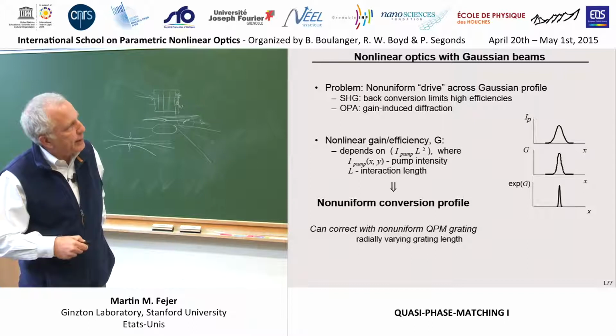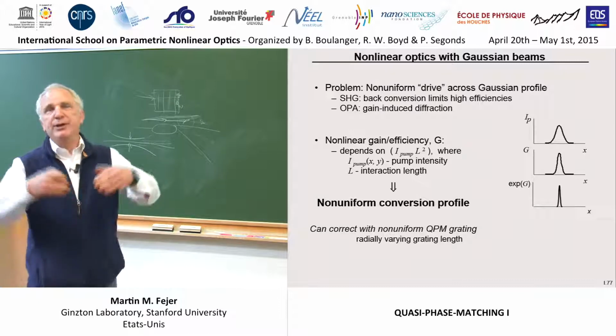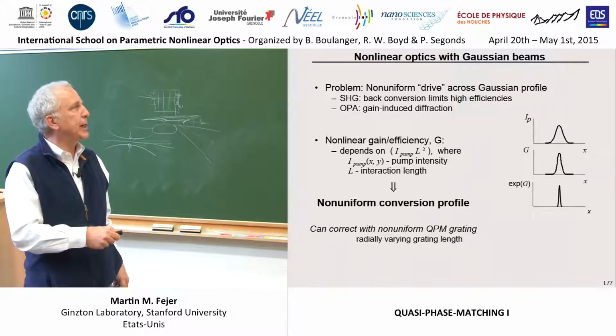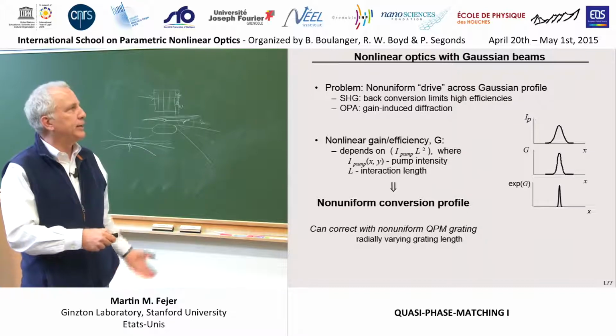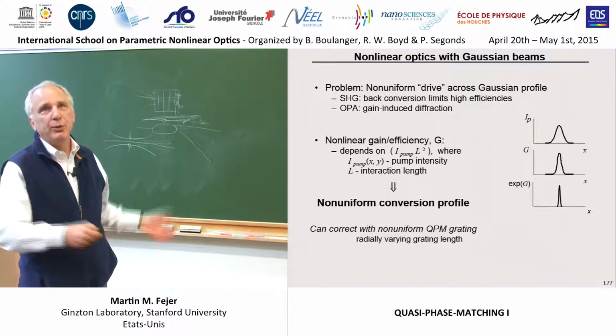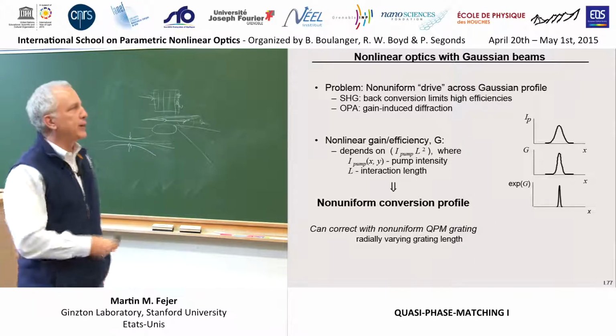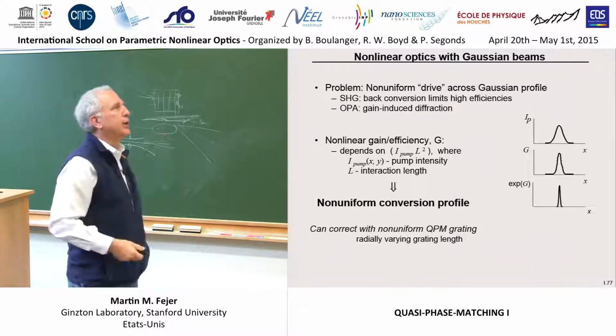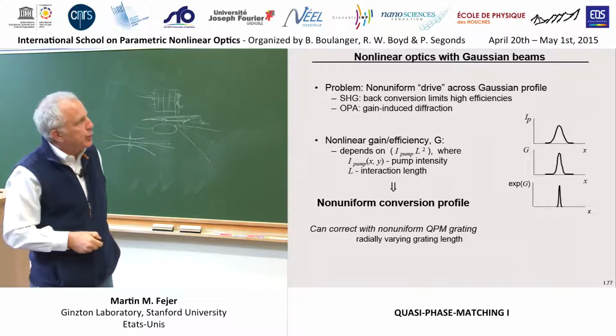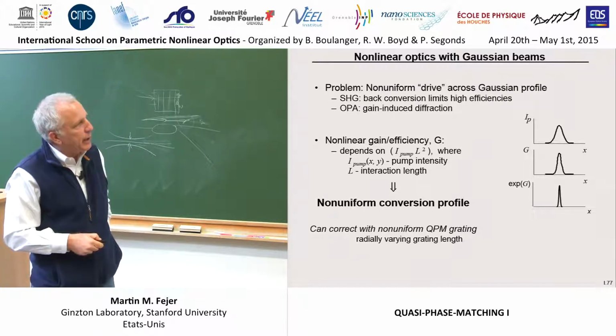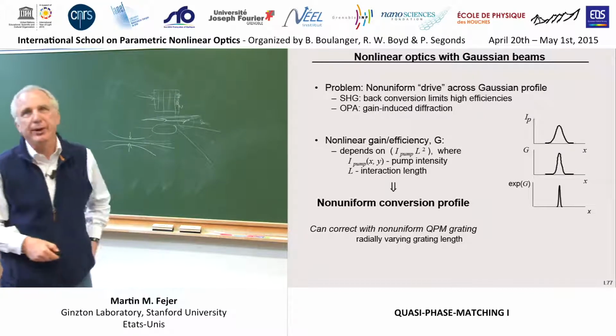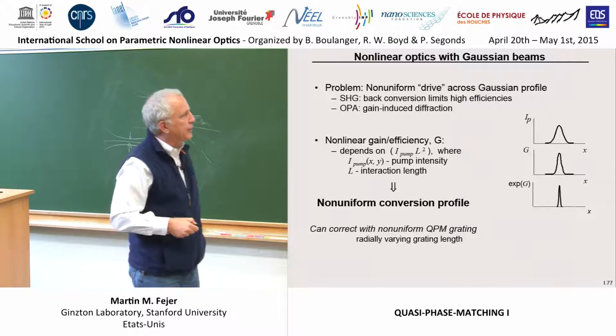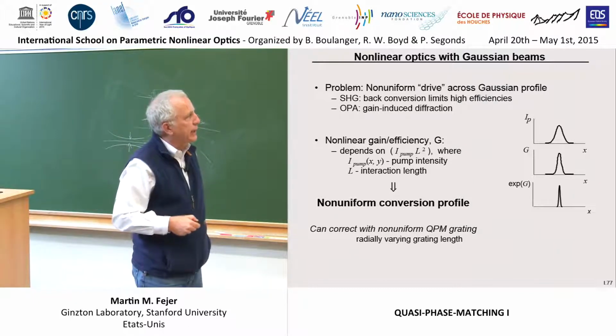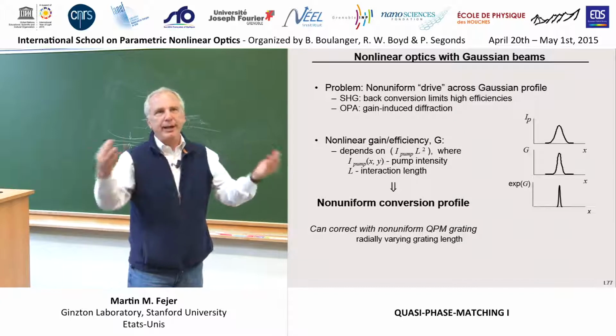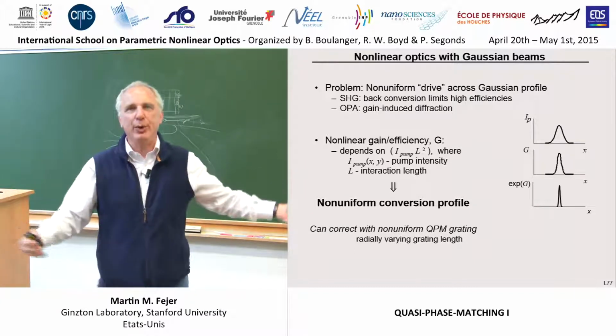If you're in an exponent like this, when you're at the half power point of the intensity, you're at the square root of the gain. So if this thing had 10 to the 5 gain at the top of this Gaussian, it has 10 to the 2.5 gain down here, which means the gain is spatially narrower, and if this is a pulse in time, it's temporally narrower than what you're pumping with, which means you might operate efficiently near the peak here, but out in the wings, the thing doesn't work very well. And if you drive it hard enough to get the wings to start to behave usefully, now you're overdriving the middle, and you're probably going to get a back conversion process or something annoying going on.